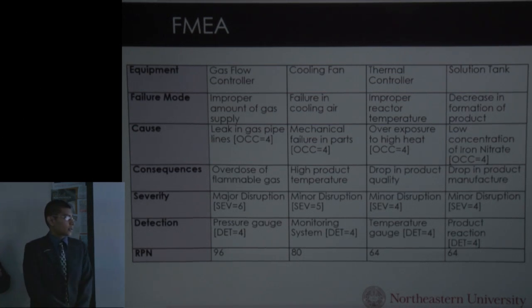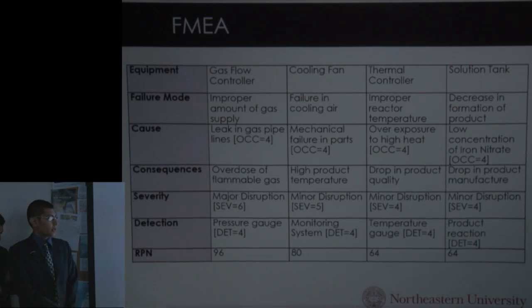Next is the thermal controller. Like I mentioned before, there's a set temperature range that the tube furnace can obtain. If the temperature goes above the required temperature, then again the process is hampered and our product quality decreases. Finally, there's the solution tank where iron nitrate solution and silicon dioxide is present. The concentration required to react silicon dioxide with graphene, if not met with the right quantity, then the reaction and product quality can decrease.